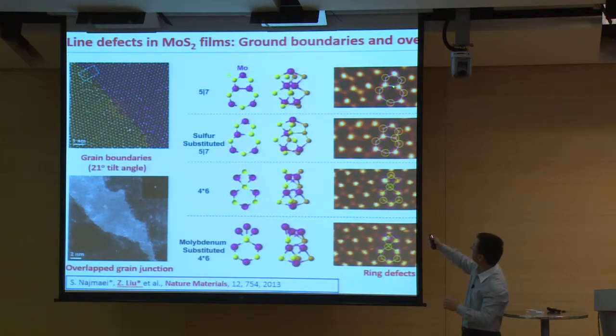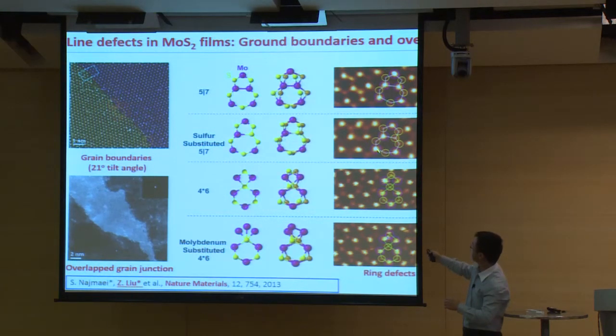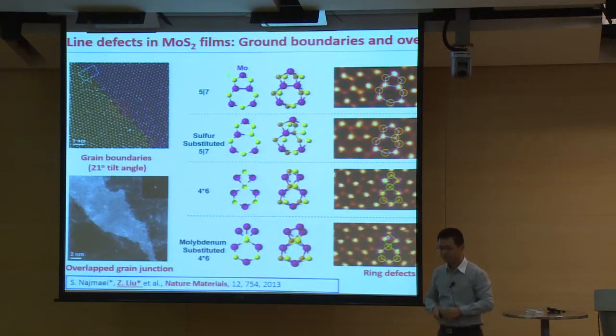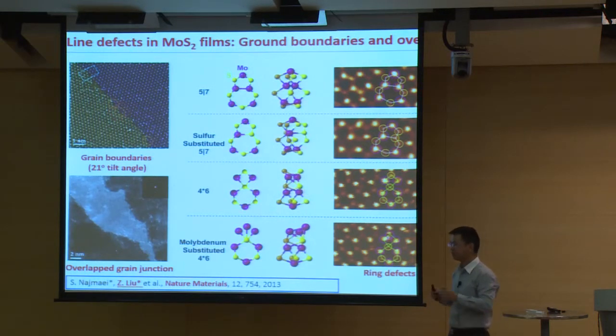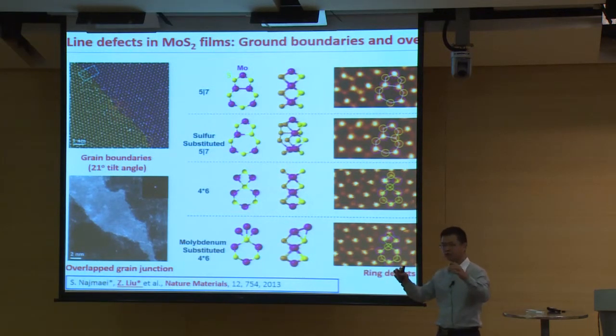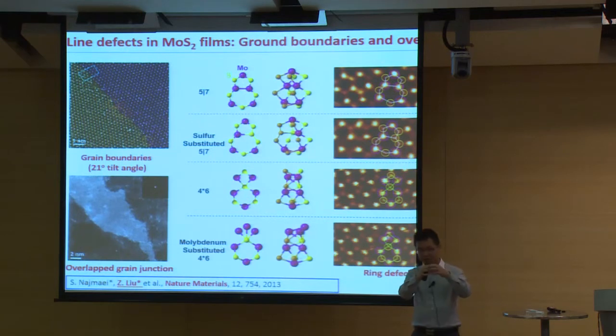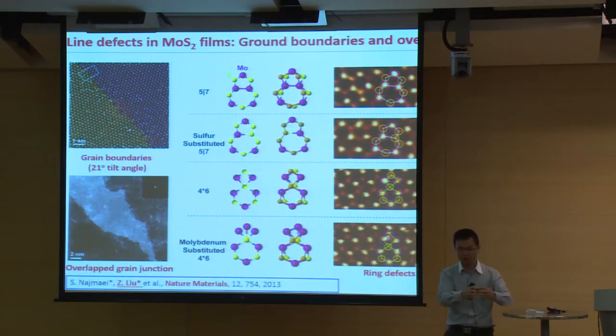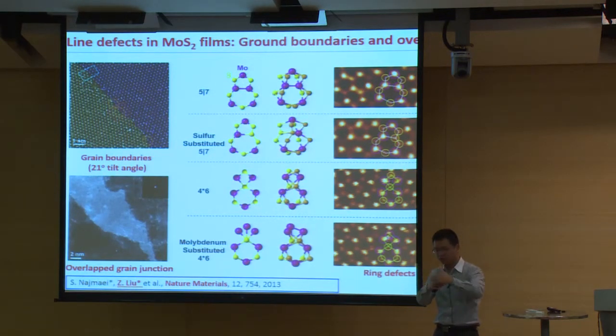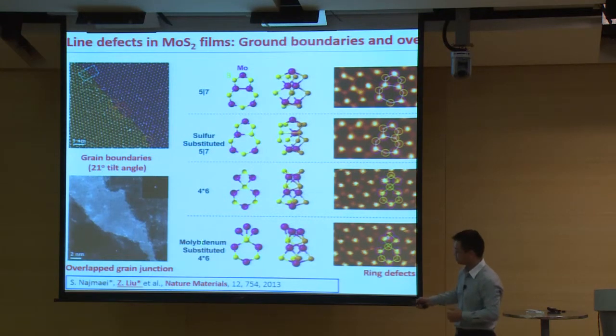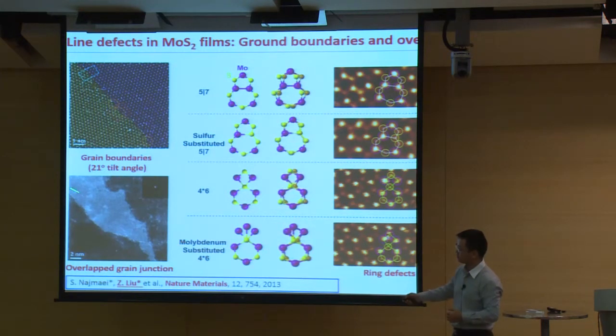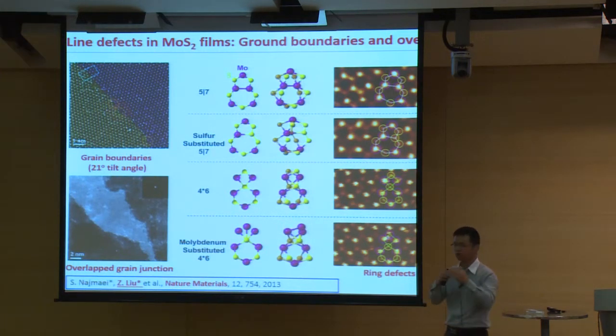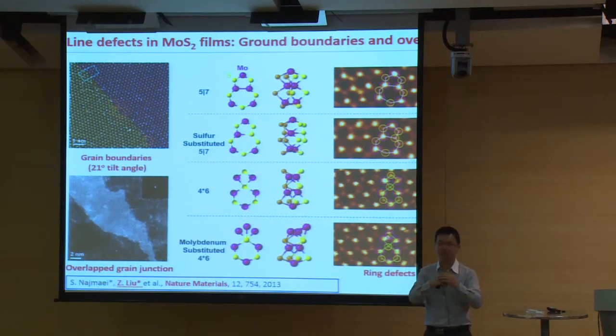and the corresponding STEM imaging showing the distribution of atoms and the shape of this ring structure. And another case is if 2 molybdenum sulfide domains grow bigger and meet each other, instead of forming a grain boundary, they keep growing on top of each other. So we can get this overlap structure. The right part is a monolayer, the left part is a monolayer, and this is the overlap of the 2 monolayer molybdenum sulfide.